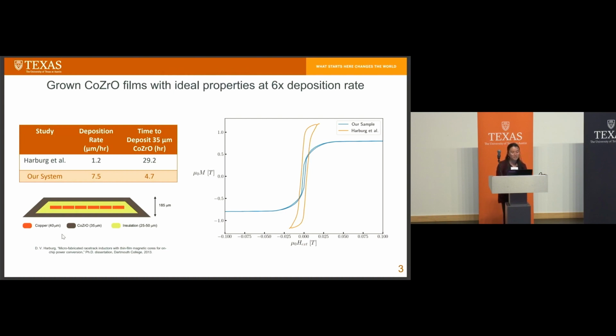Besides being a lot faster, our system can actually produce films with good properties. On the right, these are two measured hysteresis loops, one of our samples and one from the Harburg study. Just so you know, the area inside the hysteresis loop is lost for inductors. So what we're trying to do is minimize the area of these hysteresis loops. You can see that using that metric, our sample in blue has a much thinner, lower area loop, which indicates that it's lower loss than even Harburg's.